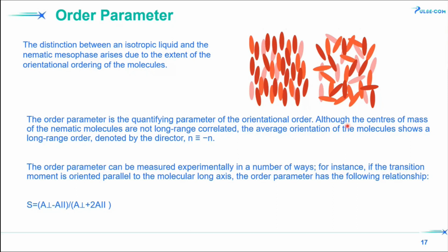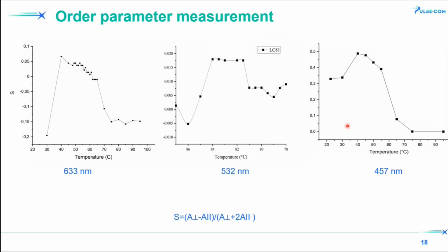In the condition, whatever you use, that will help you understand what is the best condition to have a nematic phase, so the best order possible. Usually, with our approach that we're going to explain, you're going to have a range between 0.3 and 0.7. 1 will be the perfect condition. Of course, that will never happen. And the equation that you see is the empiric equation that will help you to calculate this parameter.